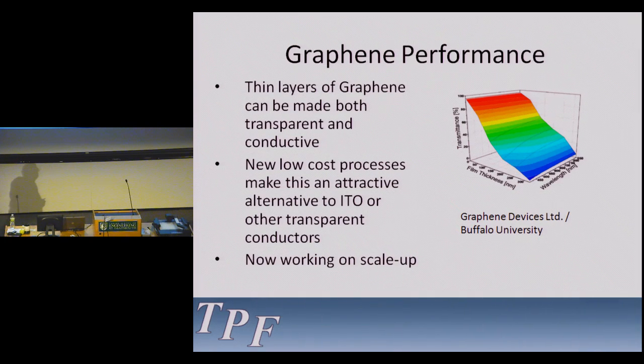And what's nice about graphene is it really doesn't have any color, and you can trade off thickness. The thicker it is, the more conductive it is, the less transparent it is. So you can trade it off to get the kind of conductivity that you need. It's potentially very low cost. And there's a company, again, that I'm working with that's working on scaling up this process. Pretty interesting.